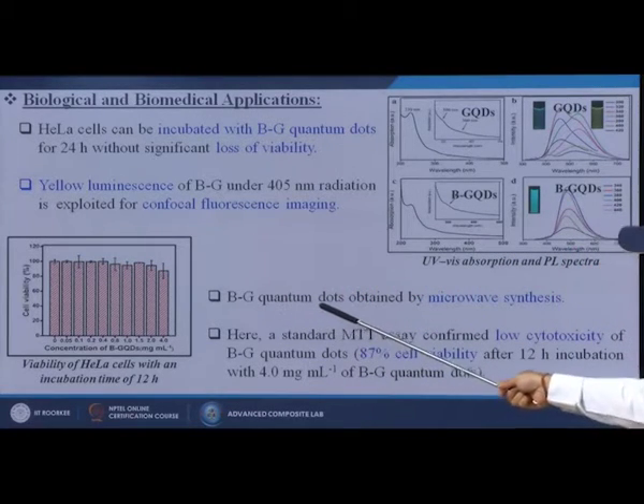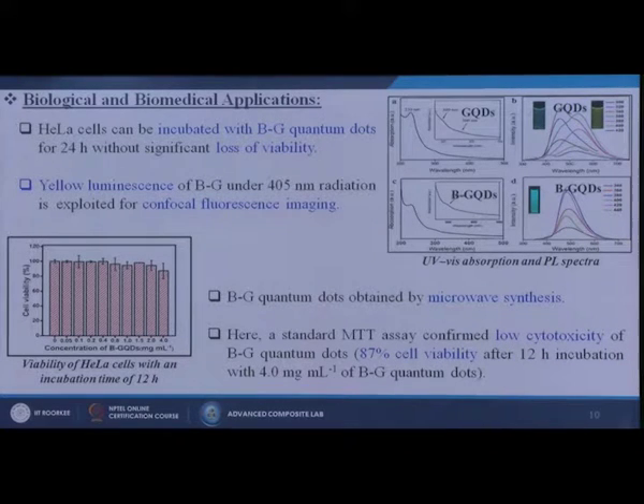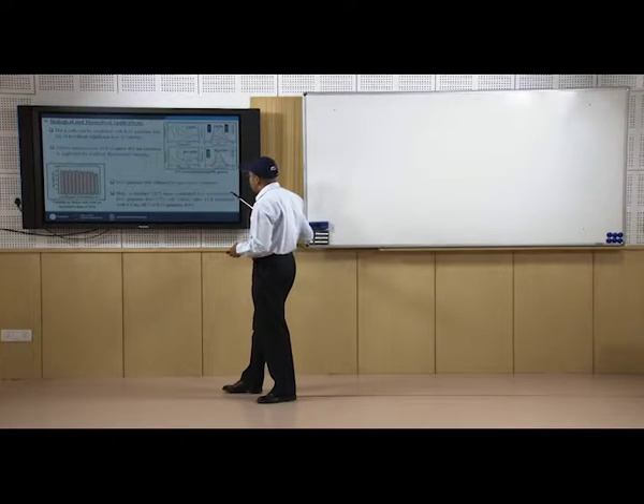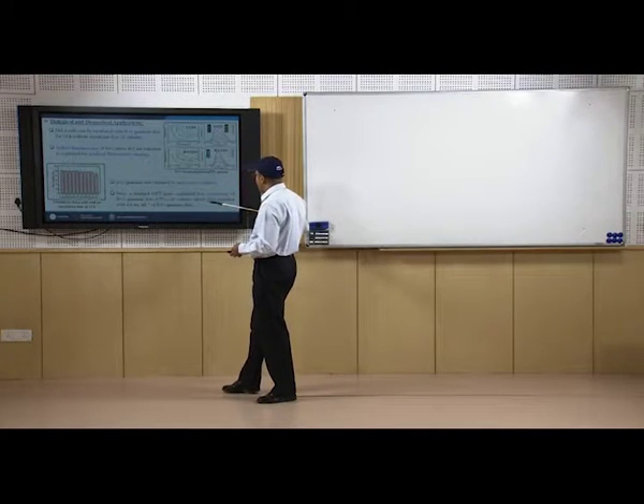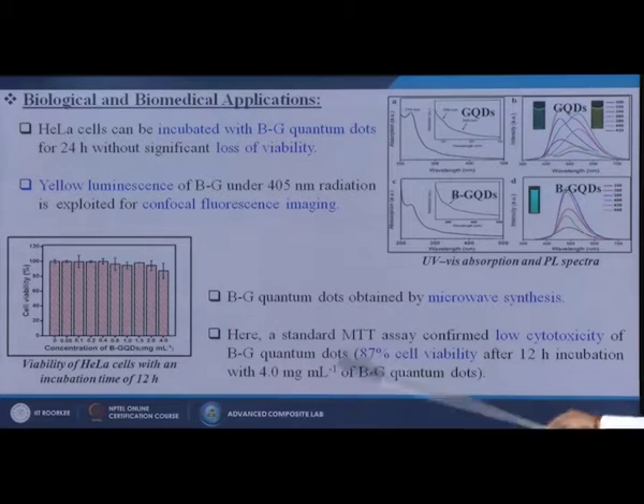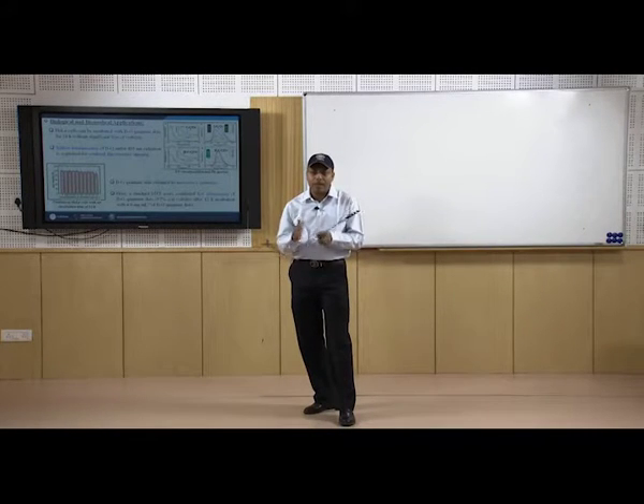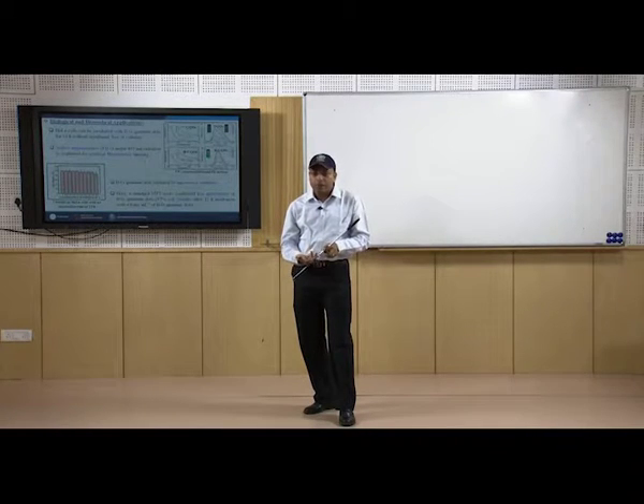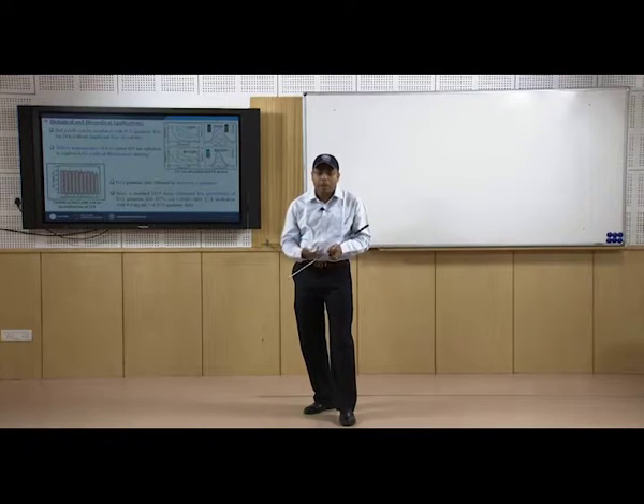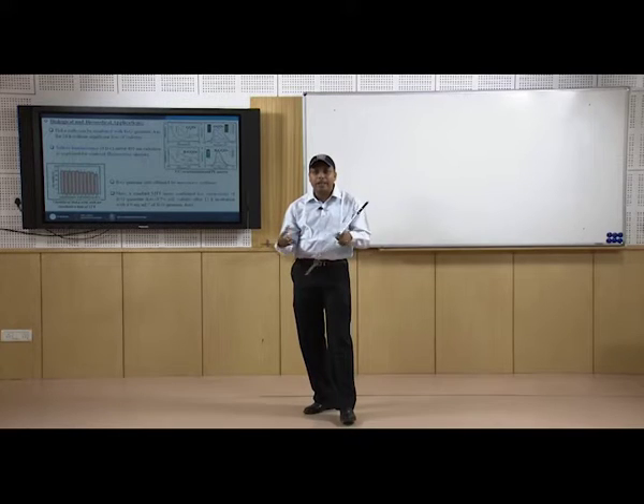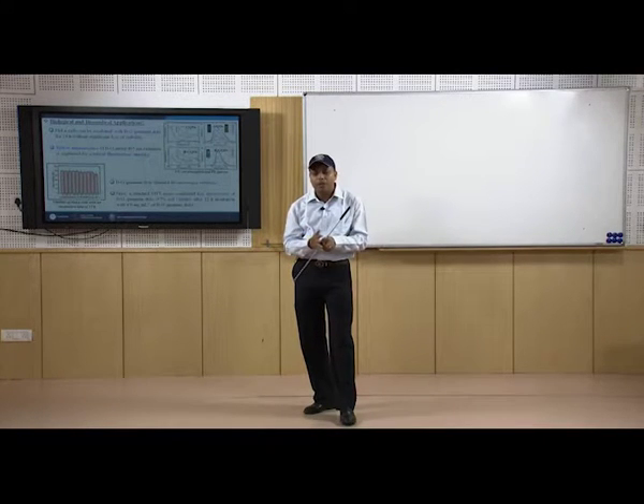Boron graphene quantum dots were obtained by a microwave synthesis process, by which we made this doping of the graphene quantum dots. A standard MTT assay confirmed low cytotoxicity of boron graphene quantum dots: 87% cell viability after 12 hours of incubation with 4.0 milligram per milliliter of boron graphene quantum dots. That means even when I increase the doping material in these cell systems, 87% of cells are alive. So I can use these materials for future biomedical applications, such as implants, lenses or stents, to enhance mechanical properties and other important parameters without harming our body systems.